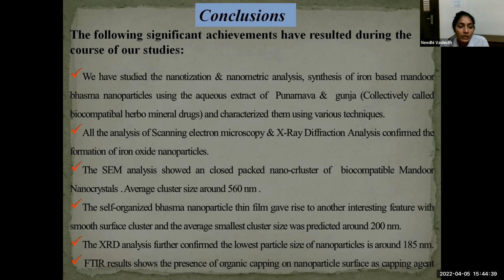560 nanometers. The self-organized Bhasma nanoparticle thin film gave rise to another interesting feature with smooth surface clusters, and the average smallest cluster size was predicted around 200 nanometers. The XRD analysis further confirmed the lowest particle size of nanoparticles is around 185 nanometers. The FTIR result shows the presence of organic capping on the nanoparticle surface as a capping agent. So these are our references. Thank you so much.